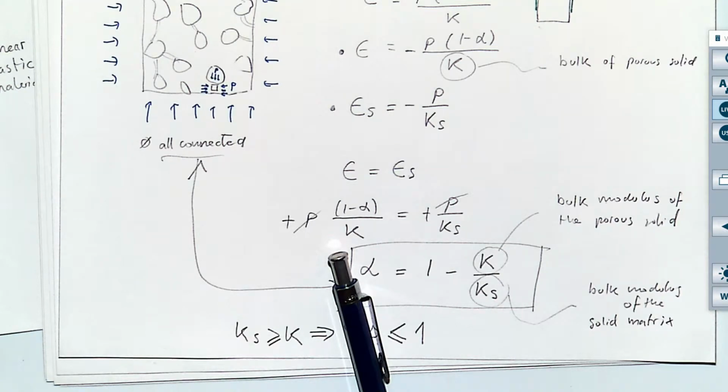Basically it's a compilation of typical Biot coefficients for rocks as a function of porosity and as a function of permeability. And basically what you see in there is that the higher the porosity of the rock, the bigger the Biot coefficient. The higher the permeability of the rock, the bigger the Biot coefficient. You go into tight rocks like shales with low porosity and low permeability, and the Biot coefficient goes down. Which makes sense because that means that the deformation goes into porosity, but also goes a lot into deforming the